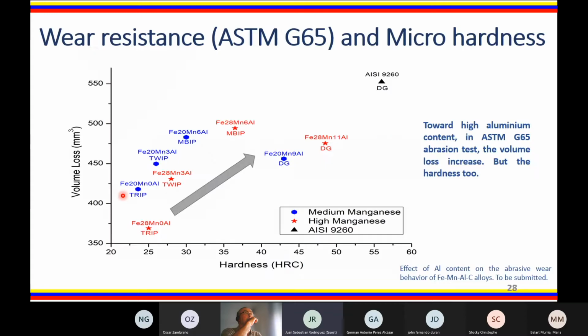Okay, after talking about processing, we will talk about some properties that we have studied on FeMnAlC steel. It is important to mention that the microstructural condition of this steel is that obtained from the thermomechanical hot forging treatment in sheet steel. The figure shows the result of abrasive rubber wheel wear. In this, a relationship is made between the loss of volume and the hardness of the material after the thermomechanical treatment. The results are quite interesting.